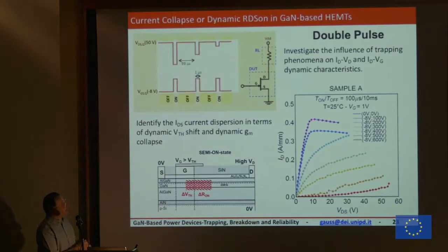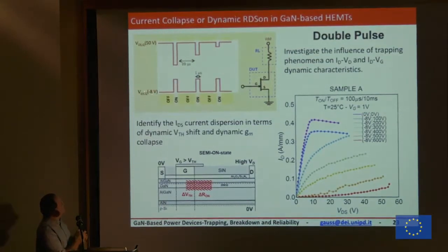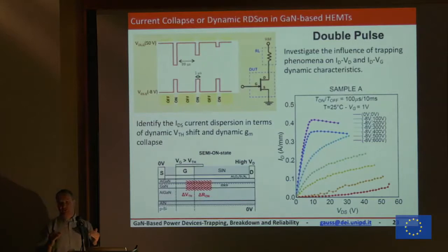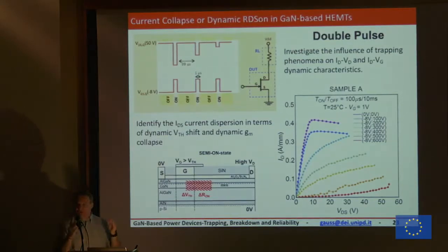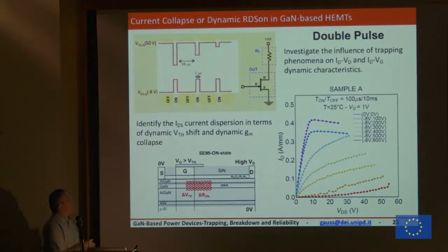So here, the first line is what we call the reference line, where the initial bias point is 0, 0. So it means that my VGS is 0, and my VDS is 0. So the device is in a quiet condition. No voltage drop across the terminals, no electric field within the device. The device, we suspect, is in a safe condition. If we then do the pulsing at the real measurement condition, we end up with these curves. So the 0, 0 curve is what we call the reference.